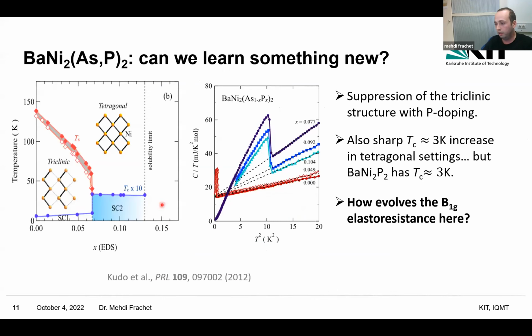Yeah. Thank you. So what we studied is this phosphorus doped barium nickel arsenide. So you see it has some similarities with the strontium sample which I showed you just before. So with phosphorus doping, we are also able to suppress the triclinic phase. And you see when we suppress the triclinic phase, there is a first order like increase in TC, which was already reported a few years ago by Kudo et al. Okay, so that's the similarity.